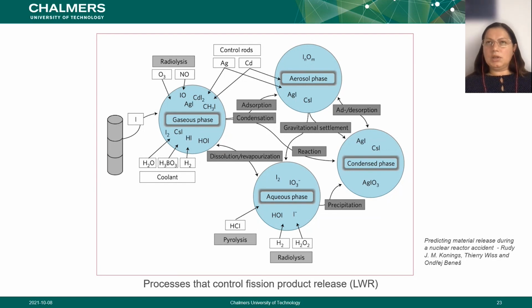You have a lot of reactions which will eventually reach equilibrium, but you can see that until they reach equilibrium, they can form different phases, and they can generate all kinds of phases which shouldn't be in the water in a reactor. So all these phases which are formed here, if the reactor is damaged in a way that the vapors can come out, all this chemistry will come out with it. So here we are only talking about the iodine chemistry. Of course, there are other materials which are not so easily reactive, which are more inert than iodine is, but some of them have even more complicated chemistry.